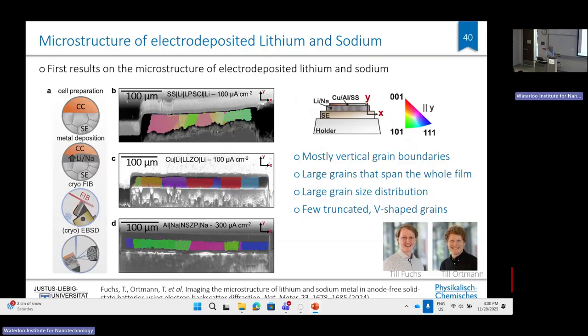And what you see here is already, I think, a major result. What they did is create a cryo workflow, FIB cutting and then ion polishing, and transfer everything under inert gas and cryo conditions. And what they then got are cross-sections of these electroplated metals: in this case, sodium on NASICON, lithium on garnet, and lithium on an argyrodite electrolyte. And the color is simply indicating the orientation of a grain.